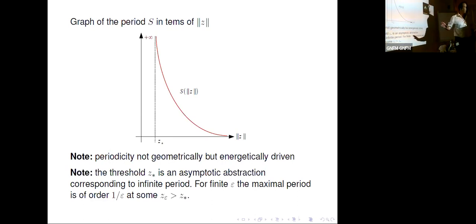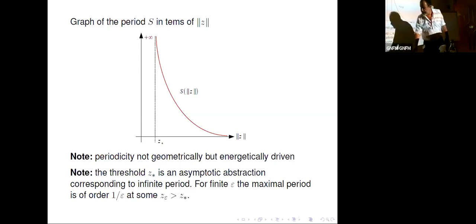And this is not due to a geometrical periodicity. There is no geometrical periodicity like here, but this is just simply energetically driven, and the period depends on the only parameter, which is the modulus of offset. It's important to see that here you have some abstraction, if you want. This plus infinity here, passing from plus infinity to a finite period, is something that you cannot do in a finite sample. In a finite sample, there will always be a gap here, and you start from some fine large but finite.